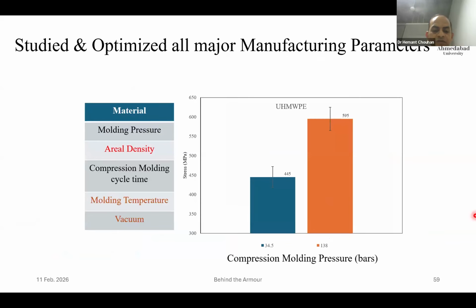The key thing about this compression molding is that we have devised the process and that is good enough. No. There are so many variables that can affect the final outcome, which will lead to variation in the ballistic properties in our case. So if I change the molding pressure, we studied this, the pressure was in PSI though. So 34.5, if I increase this molding pressure by 4 times, the same composite laminate is giving me a strength of somewhere around 450 to 600 MPa. Simply by increasing the pressure, let's say these are 10 layers, my 10 layers were resulting in 445 megapascals of strength in compression. By increasing the molding pressure by 4x, my properties are improved significantly.